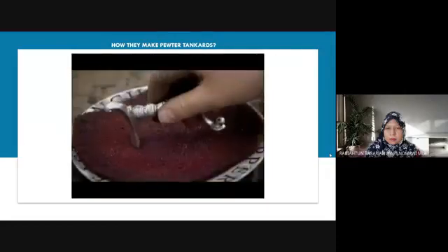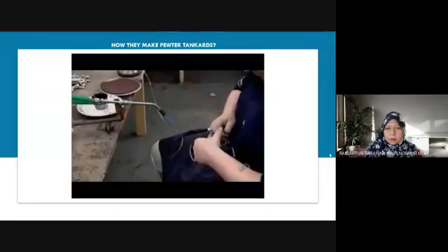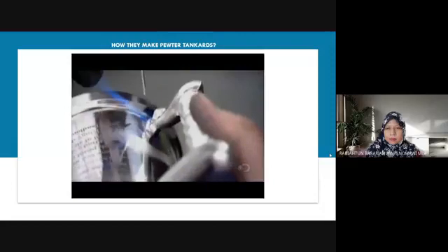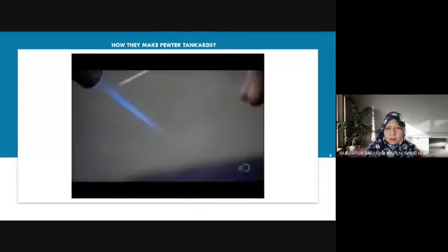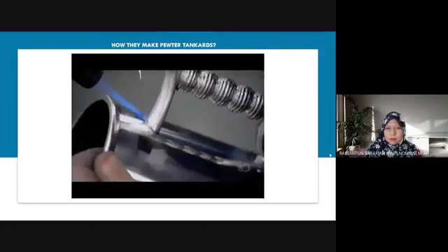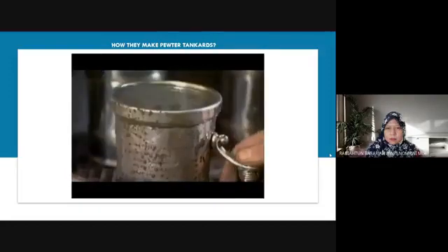Next, the metalsmith dips the handle ends in flux and solders them to the body. Avoid scorching the tankard's surface. This time, he uses a bismuth and tin solder, which requires a lower temperature to melt. The tankard is now fully constructed.